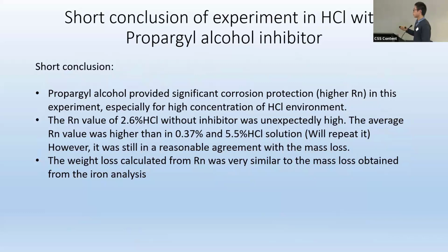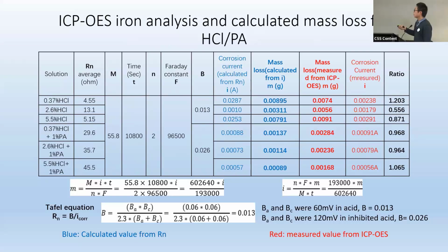So here's a short conclusion. The propargyl alcohol provided significant corrosion protection, especially for higher concentrations of HCl solution. And the Rn value of the 2.6 HCl solution without inhibitor was a bit unexpected, but it showed, I'll go back, it showed some reasonable information. It got the lowest measured mass loss in these 3 sets, and it also got the lowest mass loss from the calculation, and it got the highest Rn value. So there could be some problem in the experiment, but it showed reasonable results.